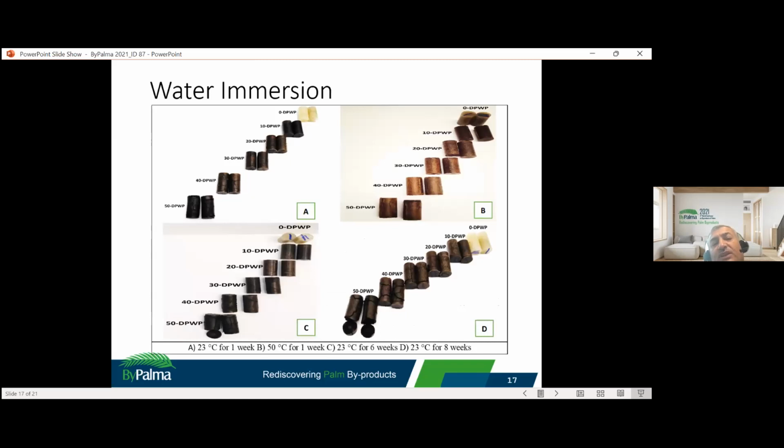If we check the water immersion for long term, we found that our material, when put in water for long term, weeks actually, starts to crack after maybe 2 weeks. After 2 weeks it starts to get some cracks. Now deterioration of the samples after 6 weeks shows that the damage or deterioration appears in the samples with high filler content in general.